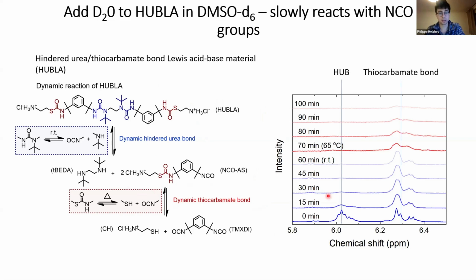So here's an NMR with deuterated water. And essentially what happens is, it takes time for deuteration to take place. So over time, we would expect the hydrogen peaks to vanish the moment the deuterated water goes into the structure and replaces the hydrogens. So the hub over time, the signal vanishes because it more and more reacts with the D2O. And so that's a signal that the first reaction happens, the dynamic hindered urea bond, and then we anneal it to higher temperatures at 65 degrees. So we increase the reactivity, and that's when the thiocarbamate bond, this one, slowly disappears because of the D2O. And it was sort of like a first sign that our dynamic covalent bonding is indeed working.